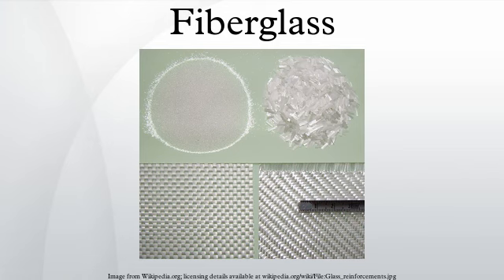Storage tanks. Storage tanks can be made of fiberglass with capacities up to about 300 tons. Smaller tanks can be made with chopped strand mat cast over a thermoplastic tank which acts as a preform during construction. Much more reliable tanks are made using woven mat or filament wound fiber, with the fiber orientation at right angles to the hoop stress imposed in the side wall by the contents. Such tanks tend to be used for chemical storage because the plastic liner is resistant to a wide range of corrosive chemicals. Fiberglass is also used for septic tanks.